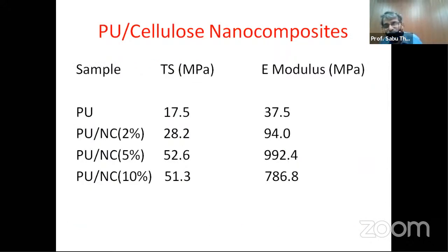I will now show you something we did with a Brazilian group in Sao Paulo. We have a cooperation with Sao Paulo where we work with nanocellulose and polyurethane. Our Sao Paulo group is very active in making heart valves. This is medical grade polyurethane manufactured by the Brazilian group. Look at the strength of the material, 17.5, 37.5. A student of mine went to Brazil. He made nanocellulose from pineapple. He mixed nanocellulose with polyurethane, 2% and 5%. When you put 5%, look at the strength of the material, 52.6. And the modulus is